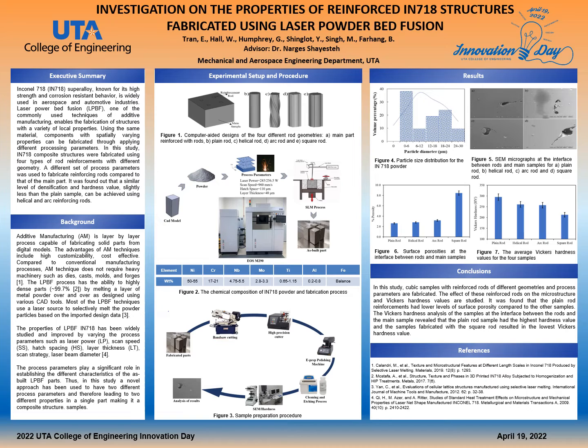Overall, in this study, cubic samples with reinforced rods of different geometries and process parameters were fabricated. It was found that the plain rod reinforcements had a lower level of surface porosity compared to the other samples. The square rods, however, had a high percentage of surface porosity due to the sharp edges. The Vickers hardness analysis of the samples revealed that the plain rod sample had the highest hardness value, and the samples fabricated with the square rod resulted in the lowest Vickers hardness value.